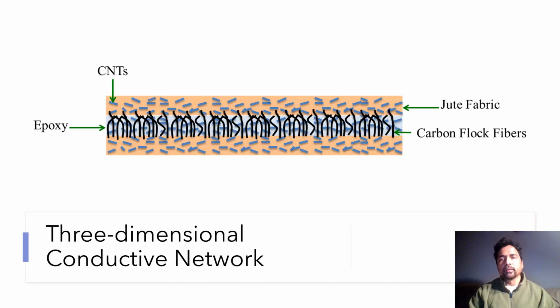In this study, we wanted to make it multifunctional. To make it multifunctional, we add carbon nanotubes and carbon fibers in the composite. As you see in this picture, carbon nanotubes are infused in the epoxy matrix, which has been used in the vacuum infusion process, and carbon fibers are reinforced in between the laminates using an electroflocking technique. This combination of carbon fibers and carbon nanotubes will generate a conductive network which is three-dimensional in nature, giving us a very sensitive network under mechanical loads to monitor the damage in these systems.